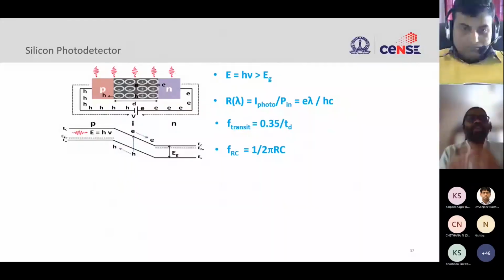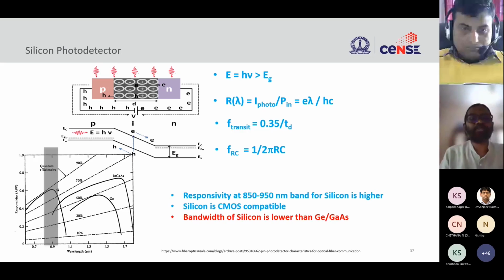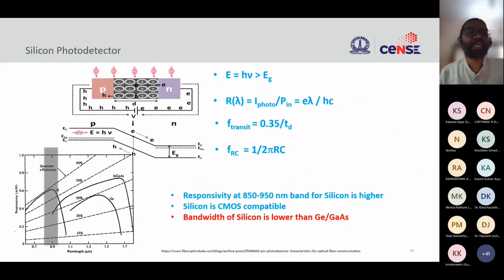Now the question is, we have made this wavelength filter. Can I make a complete integrated spectrometer? What I mean by that is I'm splitting the wavelength, but I also want a photodetector integrated in this filter. And silicon is a well-known material that is very efficient in the visible range, or in the near IR range, till about 900, 950 nanometer. The responsivity is very good. You can see here the responsivity of silicon is reasonably good, compared to even Ge or GaAs in this range. So based on the calculation, we said we should be able to use silicon as a photodetector.